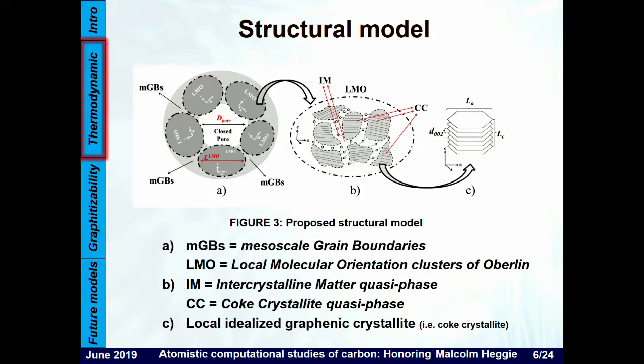So this is the structure that I chose to consider in my model. You have essentially at the mesoscale LMOs, which are local molecular orientation clusters, which were first proposed by Dr. Agnès Oberlin of the French carbon group. Between these LMOs, you have grain boundaries. Inside an LMO, you have what I call coke crystallites, which are local idealized graphenic crystallites. And between these crystallites, you have intercrystalline matter. So this is the structure that I consider for my model.